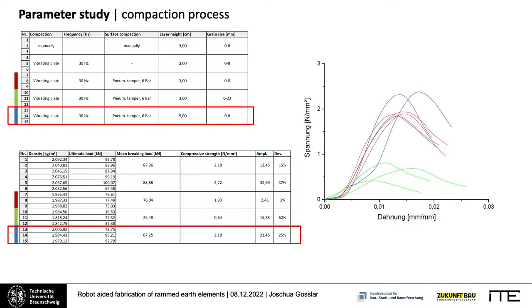And in the first test, which is the blue one here, that is now marked in red, you see the blue lines on the right side. You see that we used, I need to look it up, a layer height of 5 centimeters, uncompacted, a material with a maximum grain size of 8 millimeters, a vibrating plate with a frequency of 30 hertz, and this resulted in, from single values, the highest compressive strength we could achieve, but the deviation, you see it here on the right side, was 25%, and that was way too high for us, because what we actually aim for is a very low deviation between different samples, because of course it's an automated process, and the goal is to have actually no deviation, because we can control the whole process, and it's not related to one worker that is tamping there.